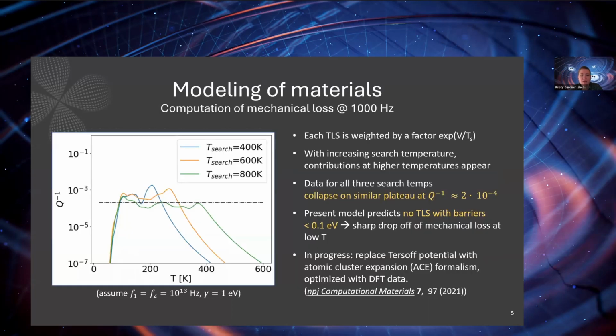They've had some really nice results recently where they carried out these simulations at different search temperatures and found that no matter what the search temperature was, the data collapsed on a similar plateau, giving a mechanical loss of around 2 × 10⁻⁴. The fact that the results were pretty similar no matter the search temperature gives a lot of faith in the robustness of these models. What they're going to do next is to replace the Tersoff potential with an atomic cluster expansion formalism optimized with DFT data to further increase the accuracy of these models and get even better predictions of mechanical loss.